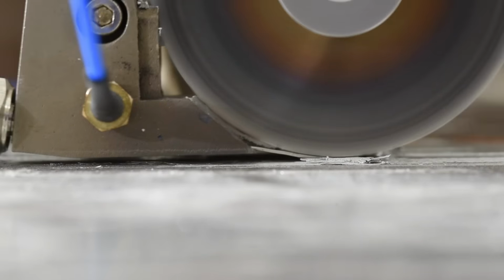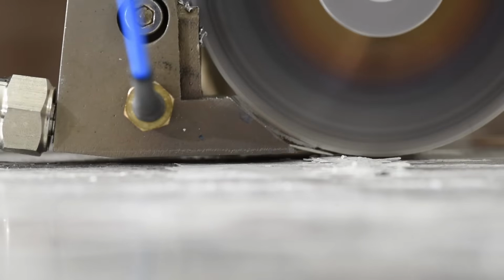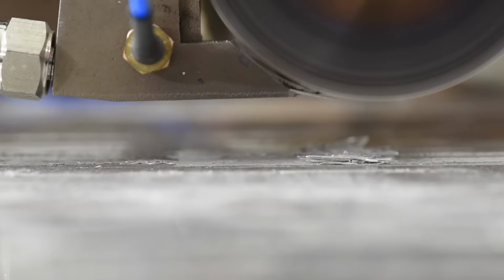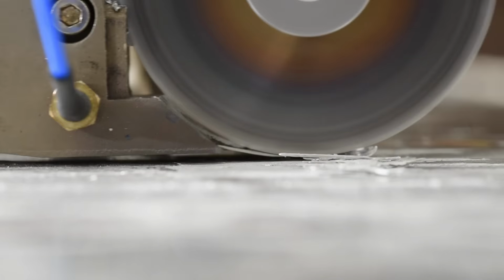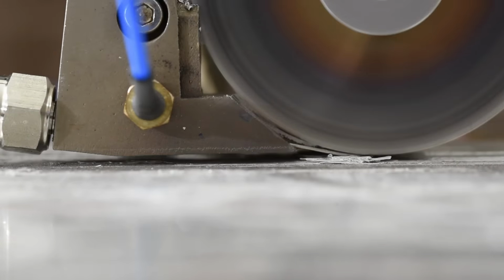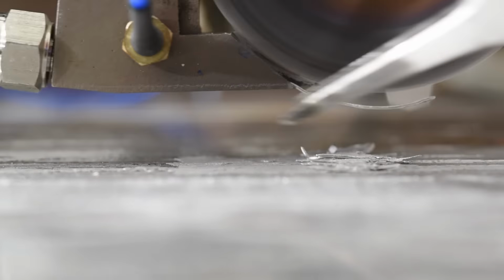And the overlap fraction changes how well the bonding between the lines happens and how well the lines ultimately end up bonding to the substrate and to each other. So this footage you're seeing now is our attempts at printing horizontal lines in the y-axis that are exactly 90 degrees to the wheel rotation direction. And it kind of works.